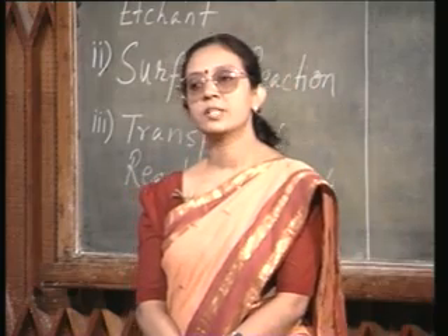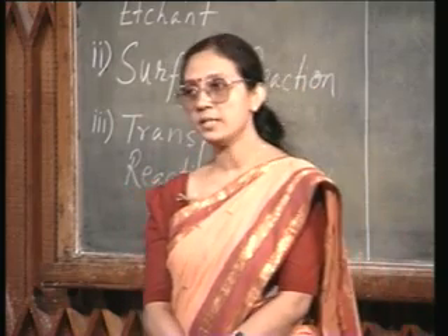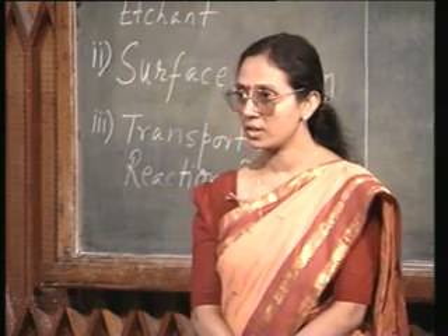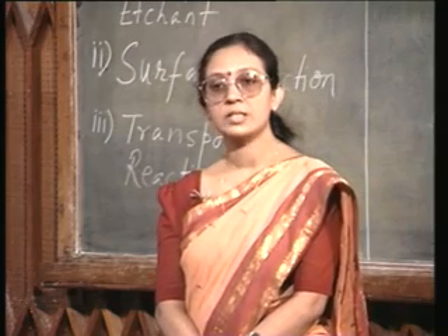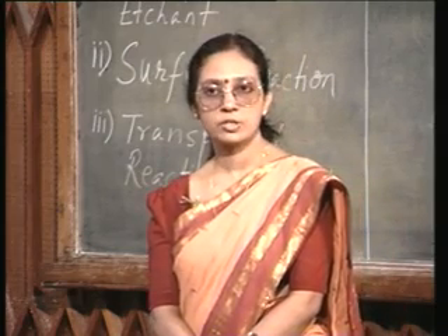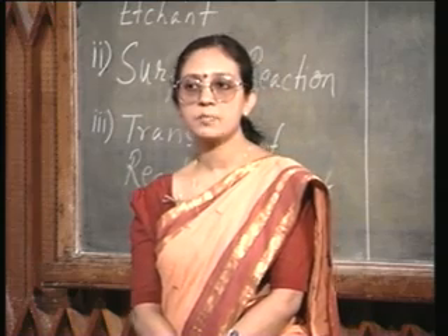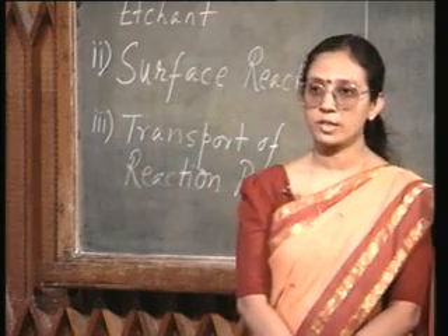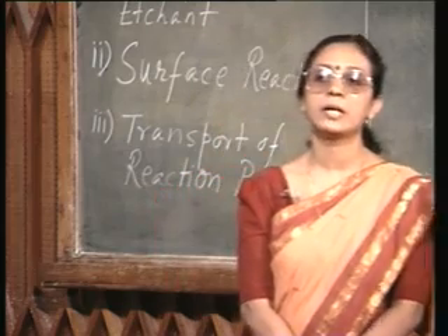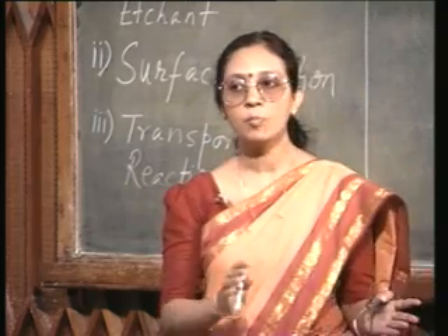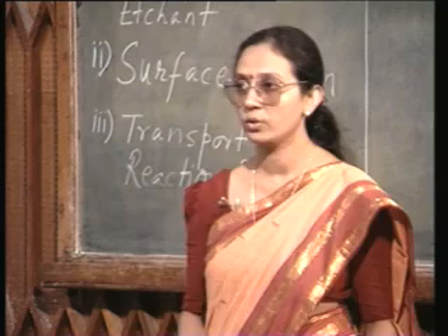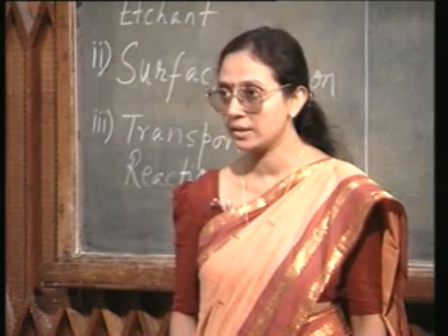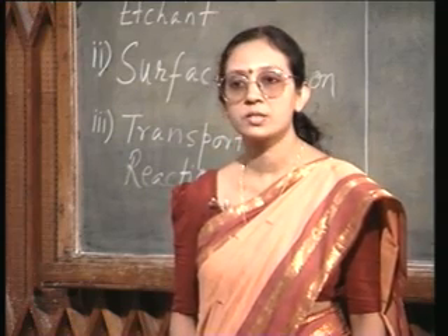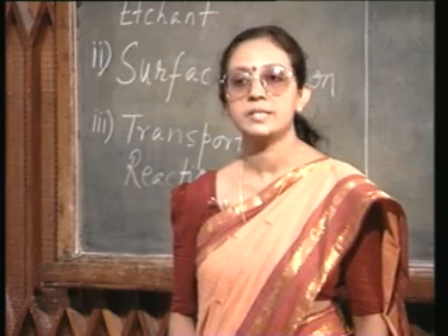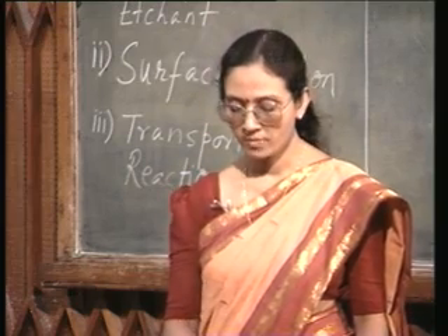So, the first step in the silicon etching is going to be oxidation, which is analogous to your anodic oxidation reaction, and the second step is going to be etching of oxide. So, invariably you will find that the silicon etchant has more than one component, more than one material in it. One is for oxidation, one is for etching of that oxide.